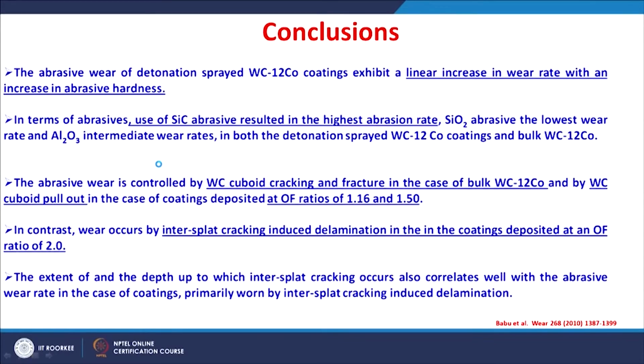Wear occurs by intersplat cracking induced delamination in the coatings deposited with an oxygen to fuel ratio of 2.0. So, this intersplat cracking induced delamination is dominant at higher oxygen to fuel ratios, and lower oxygen to fuel ratios always gave tungsten carbide cuboid pull out in the case of coatings deposited at oxygen fuel ratios of 1.16 and 1.50. In contrast, wear occurs by intersplat cracking induced delamination in the coatings deposited at an oxygen to fuel ratio of 2.0. Further, the extent and the depth up to which the intersplat cracking occurs also agrees well with the abrasive wear rate in the case of coatings primarily worn by intersplat cracking induced delamination.